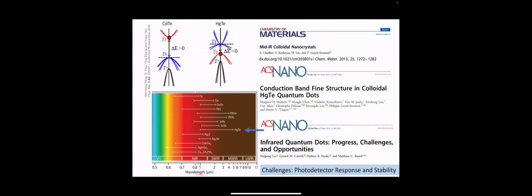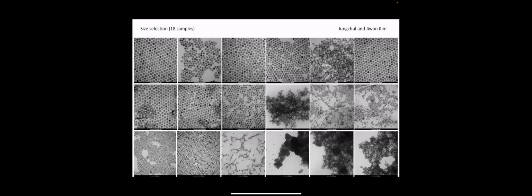So these are a few nice review papers talking about mercury telluride and IR dots, in case you want to look those up. The synthesis of mercury telluride is pretty straightforward. So I'll talk a little bit about mixing in some different ligands. But you can just make nanocrystals with mercury chloride and oleylamine and do a hot injection with TOP telluride. Mercury telluride particles, at least for us, we've found that we've got to grow at significantly lower temperatures compared to other nanocrystals. So maybe up as hot as 120 C, but these tend to be relatively low-ish temperature reactions.